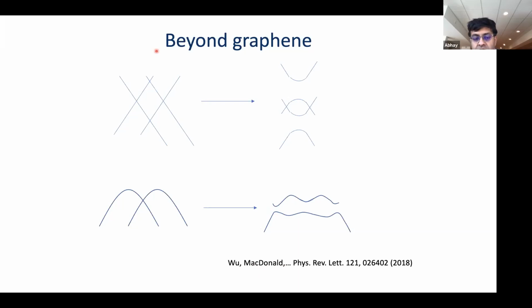So, okay, what we did is we made a sample of twisted tungsten diselenide, and then we do transport. So these are all transport measurements, nothing on STM just yet, although we have some preliminary data. And we do the same business that you do for graphene. You change the doping and you see what happens to the transport as a function of doping.